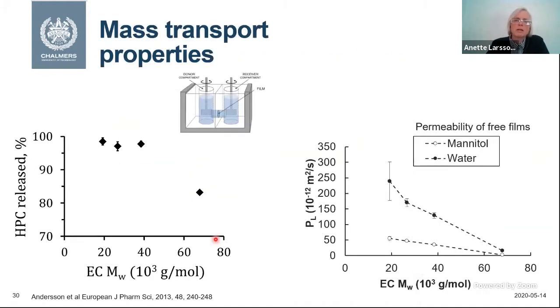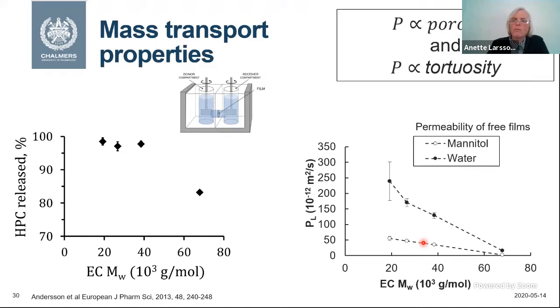it comes another thing. Here you have the same porosity, but you can still see that the permeability decreases. And what we did was that we compared the permeability for water with the permeability for mannitol, radioactively labeled mannitol. And then we could see that it was not just the porosity that was an important factor, also the tortuosity is an important factor. And tortuosity means the diffusion pathway the molecules need to take when they go through the coating.